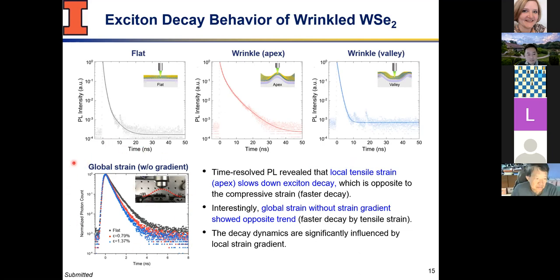Multiple groups have done this. You basically put a 2D semiconductor and use global bending. So this is not a structure with strain gradients; this is relatively uniform strain compared to our structure. And what they observed was that when you apply tensile strain, flat versus tensile, the lifetime is shortened. So higher tensile strain, shorter lifetime. We're seeing longer lifetime. So we're very puzzled at this point. We just wanted to study more, since things are not consistent with what has been reported.